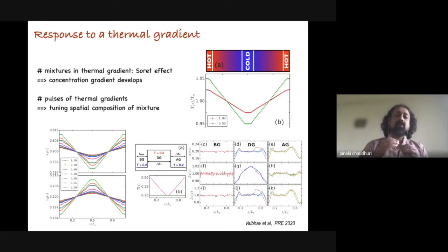And if I decrease the ambient temperature of the system, we see that these concentration profiles are becoming sharper and sharper, and near the glass transition, essentially you have a huge concentration of B species near the cold zone and a larger concentration of A species in the hot zone. So this is a physical process that is happening. Now the question is, can you take advantage of this physical process in one way?